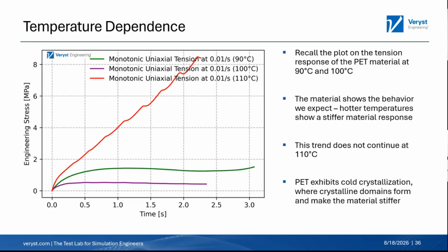But if we go to those much higher strains, you can see we're at these huge stress levels where we're 4, 5, 6 times as stiff. That's because the PET is showing cold crystallization, so we're getting a change in structure due to that heat. And as that happens, we're getting a stronger, stiffer, and ultimately more brittle material, and that's going to make our simulation process much more difficult.